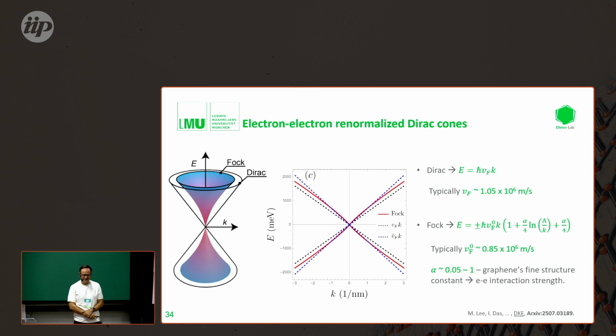This lambda is also the reason why we see this effect at room temperature: the effect is not very sensitive to temperature because lambda is so big. You are basically supposed to see this effect probably at 1,000 Kelvin as well, right?